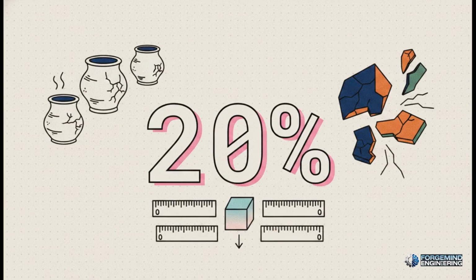We've got our shape, our green parts, but we are far from finished. 20%. That is how much a ceramic object can shrink from its original moist size purely through the loss of water during this drying phase. 20% is massive. If this shrinkage happens unevenly, the entire part will just warp or violently crack, completely ruining all of our hard work up to this point.